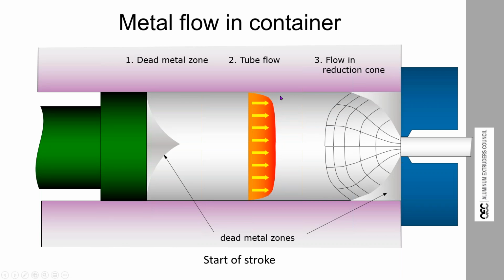So the aluminum bonds to the steel, and at the edges there's all this friction holding back the flow. And you can see here, the flow is faster in the middle than it is at the edges. And of course, we're generating a lot of heat because we're rubbing friction here. And most of the press power goes to heat. So force times distance, thousands of tons times maybe 2 or 3 feet, all gets converted into heat, and that heat has to go somewhere.